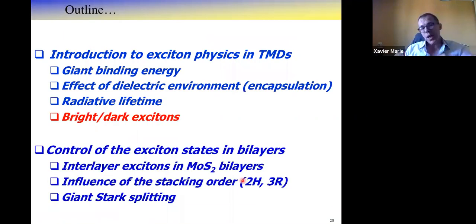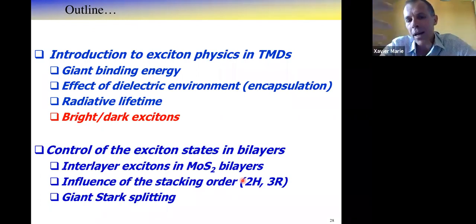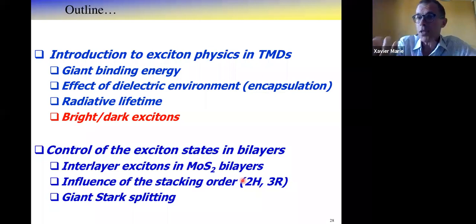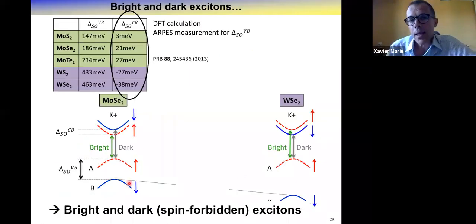Just to finish this part on monolayers and switching to bilayers, it becomes a little bit more technical, because when we deal with excitons, so far I neglected a very important, essential degree of freedom, which is the spin. How do you build your exciton? What is the spin of the electron and hole which form your exciton? A lot of work has been done in this field for 5 or 6 years. It started with a schematic representation of the band structure. You have the gap, and, not at scale, the spin-orbit splitting in the valence band I already presented between A and B, but the calculations also predict a small spin-orbit splitting in the conduction band, a few tens of millielectron volts.